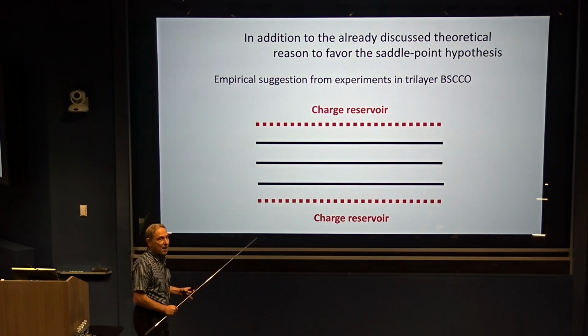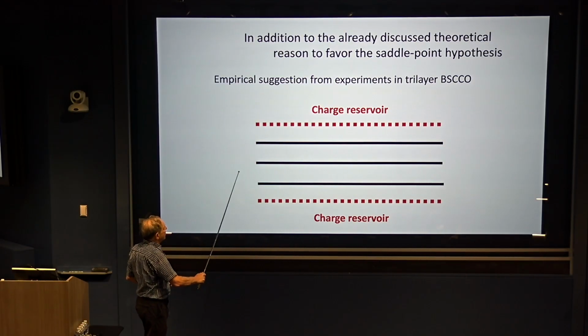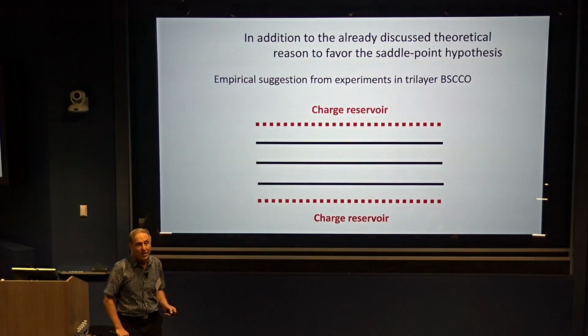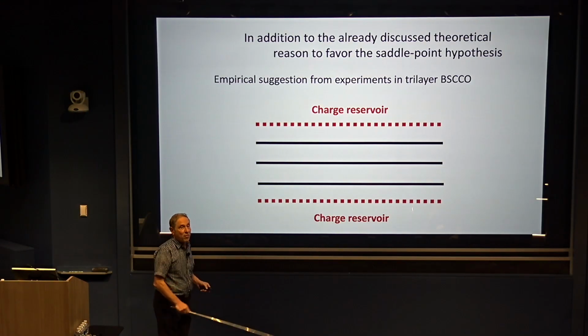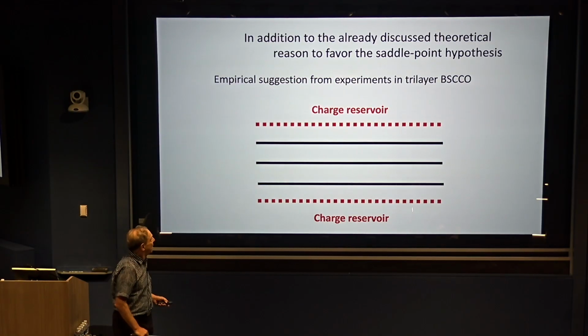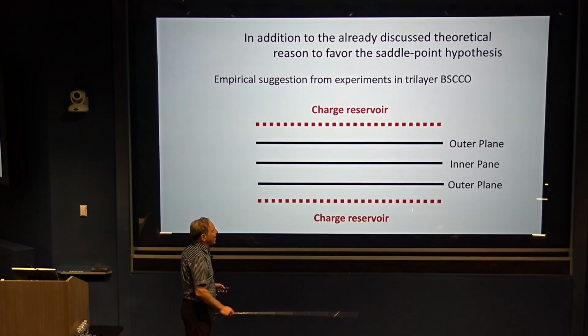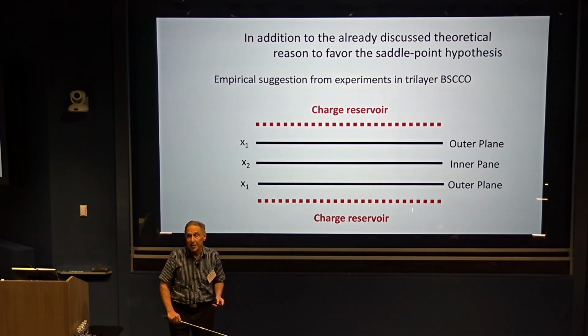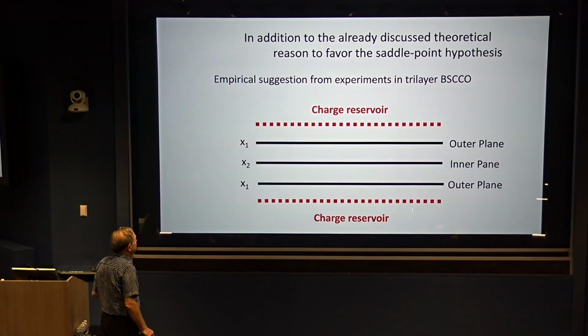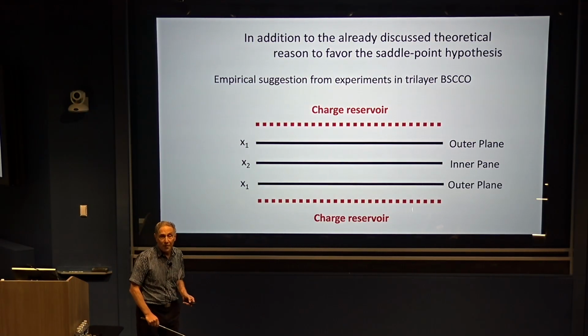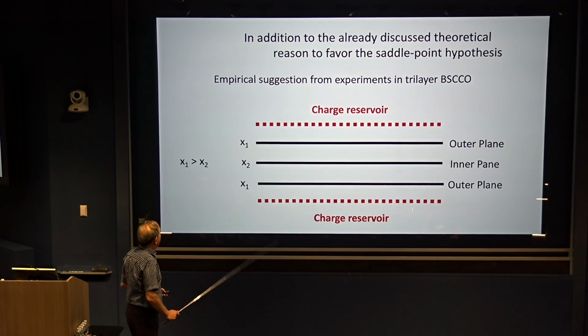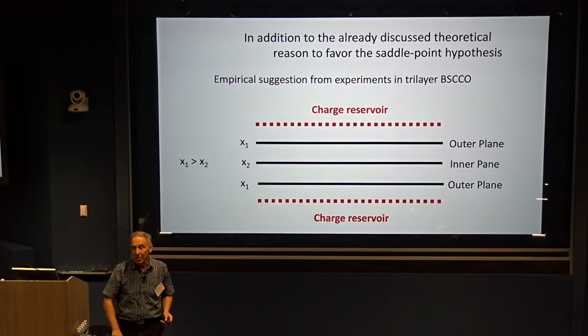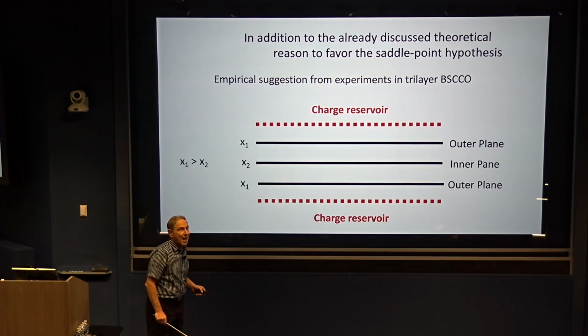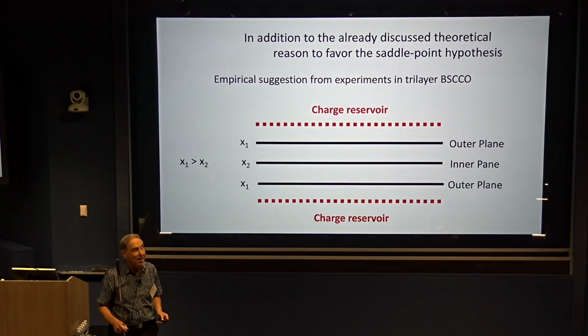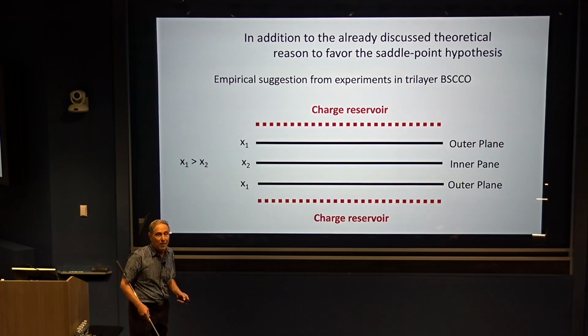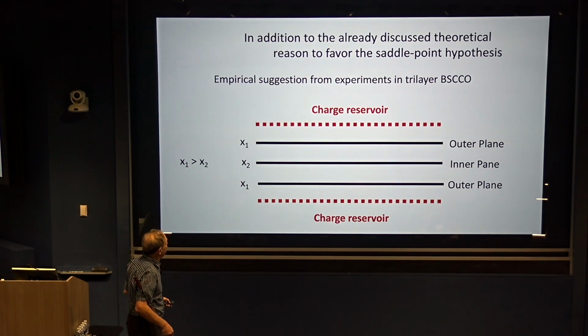So tri-layer BSCCO looks like this. There's the charge reservoir layers, and then there's 3 copper oxide layers. And the inner layer and the outer layer are crystallographically inequivalent to each other, which means that for sure the outer planes and the inner planes will have different doping concentrations. So this is the sort of situation that we're interested in. And because the charge comes from the charge reservoir layers, in fact, what we expect is the outer layers will be more heavily doped than the inner layers. So this is the sort of situation that we might hope this physics plays out in.